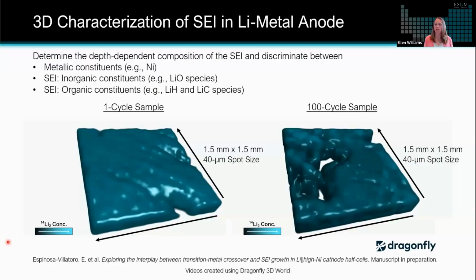But the key point that I want to identify here is how LALI TOF-MS is helpful in identifying not only the metallic constituents that were also seen with some of the X-ray techniques, but also these SEI constituents. So what you're looking at here is two lithium metal anode samples, one of which had only undergone one cycle, the other of which had undergone 100 cycles. And when I play these videos, you'll see these different lithium species that our colleague Eric has interpreted as representing both the inorganic constituents, so mostly the oxide species, as well as some of the organic constituents of the SEI. So wherever you see lithium combining with hydrogen or carbon, for example, those represent the organic constituents of the SEI.